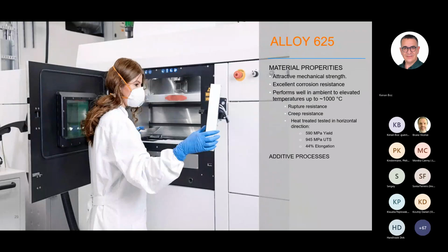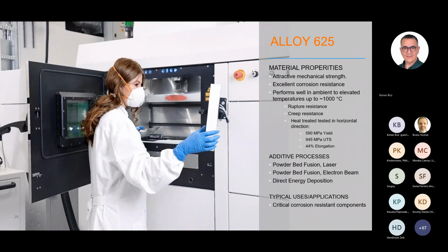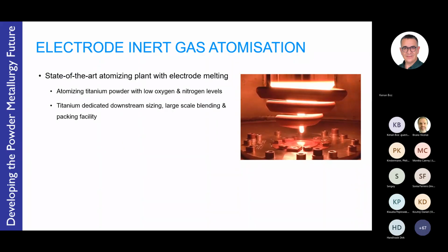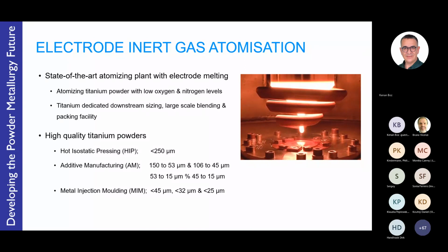Now moving on very quickly to another example, Inconel 625 has very high corrosion resistance and can operate at high temperatures. And yes, good when it comes to critical corrosion as well. And electrode inert gas atomizing. So here we can see, as I said, dedicated processing of the material under inert conditions, producing a wide range of different sizes, from hot isostatic powders to powders suitable for direct energy deposition or electron beam melting and laser powder bed fusion, and a growing interest in fine applications for metal injection molding. And there are now some initial machines in binder jet printing that are producing titanium components as well.